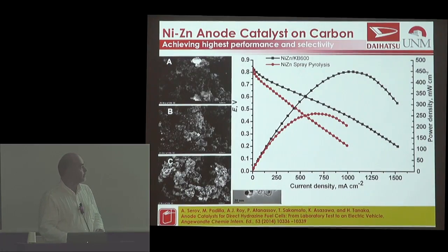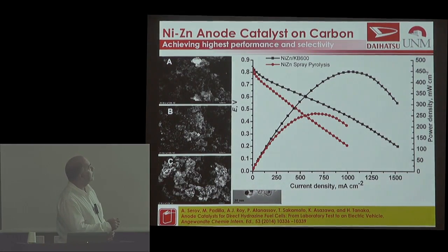And when you do this catalyst well, put it on a Ketjen black, you obtain the highest possible power performance of an alkaline membrane fuel cell that is done entirely without any noble metals at all. No platinum, no palladium, no ruthenium, nothing. So this is just an example of how one can engage metallic systems.